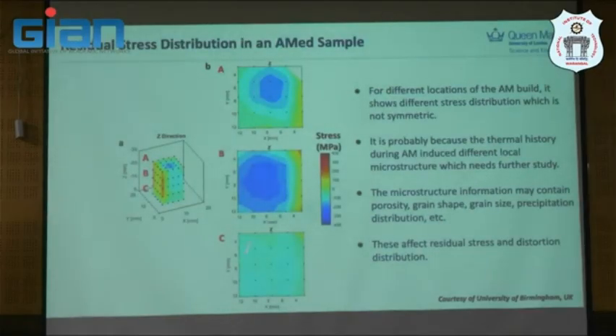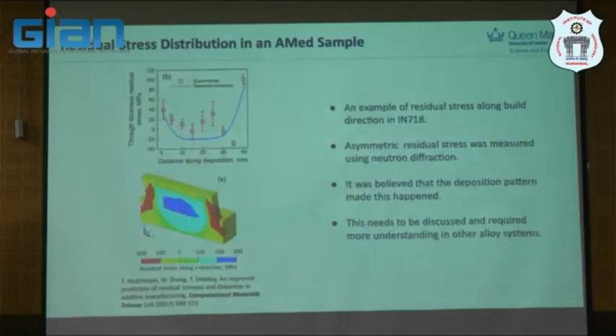If you map across different locations here, you will see the maximum residual stress at different locations is also different. So there's some combination of compressive stress and tensile stress in this one sample. So we need to be careful, especially as scanning pattern will contribute to that as well. So I mentioned 4 parameters now that we may need to be careful about, because the microstructure information of the sample will be so significant. We talked about defect content previously that contributes to this residual stress. I think this is a proof that I'm trying to say from an experiment point of view.